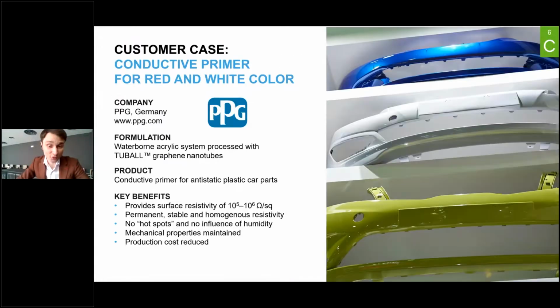And let's move forward. There are a lot of different applications. The next one is conductive primer with a very low surface resistance, which is required for high transfer efficiency of the base coat. And here it is crucial to provide excellent adhesion of the base non-conductive primer to the substrate, and we can do it. TUBALL allows to maintain mechanical properties and provide the most commonly used 500 kiloohms per square.